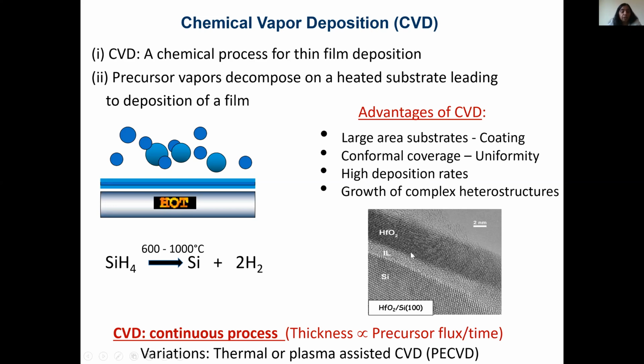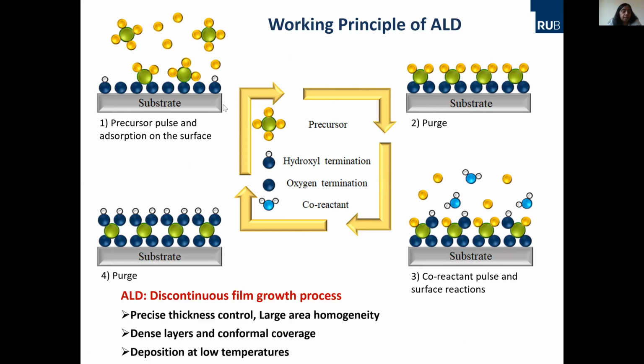Now, in the case of atomic layer deposition, as I said, it's a pulse and purge process, so it's a discontinuous process, unlike in the case of CVD. Because of this discontinuous process, you can have a very precise thickness control. Again, as in the case of CVD, you have a very large area of homogeneity, very dense layers, and also conformal coverage. Most importantly, you can grow the films at very low temperatures.